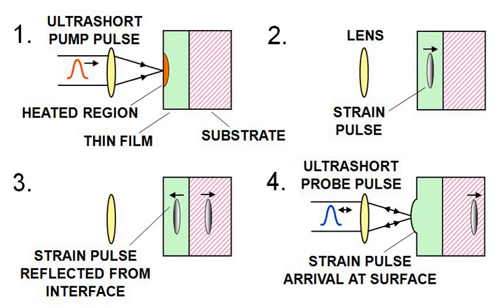Strain pulses returning to the surface from buried interfaces or other subsurface acoustically inhomogeneous regions are detected as a series of echoes. For example, strain pulses propagating back and forth through a thin film produce a decaying series of echoes, from which one may derive, in particular, the film thickness, the ultrasonic attenuation or the ultrasonic dispersion.